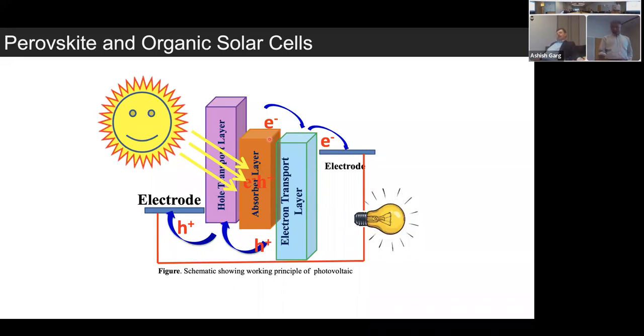So it's unlike silicon where you have to form a PN junction. Perovskite is, for example, an ambipolar material. It allows the transport of both electrons and holes, whereas in organic solar cells, you rely on the blend of p- and n-type materials for electrons and holes to be separated. This absorber layer could be about 100 nanometers in organic solar cells, and about 0.5 micron to 1 micron in perovskite solar cells.